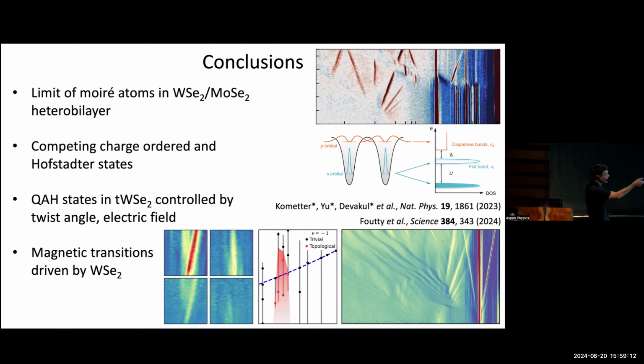Yeah. I don't know what you mean by no, but this little purple strip here is really, really weird. You have a mixture of light and heavy bands. In some sense, this sounds like Kondo lattice physics, like traditional heavy fermion compounds where you have local moments and itinerant conduction electrons, and there's some interaction between them. It's not that, because here all the spins are fully polarized, so you can't form Kondo singlets in this case, but nonetheless, you still have this coexistence of light and heavy bands. The degree to which they hybridize, we have no idea. What exactly is the nature of these states? Again, they're vertical, so that means you have a certain carrier density. It's partially heavy fermions, it's partially light fermions, and somehow together they are forming some commensurate arrangement of charge, some commensurate electron solid. How these are arranged, again, we have no idea what exactly is going on in that particular strip there.